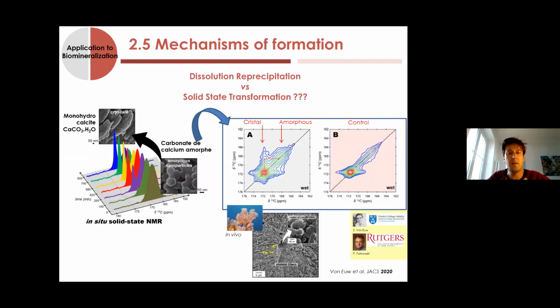Again, this is the example of some calcium carbonate samples coming from corals, and you see that the transformation from the amorphous phase to the crystalline phase is actually a solid state transformation.